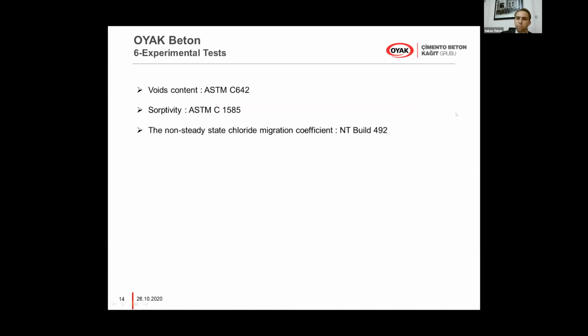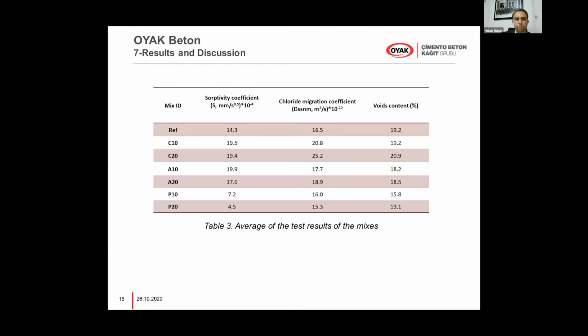And as I said, we have the previous 3 different test methods. One of them is void content in accordance with ASTM C642, the sorptivity test ASTM C1585, and chloride migration coefficients in accordance with NT Build 492, which we have already performed. Here you can see all the results. The reference mortar has a sorptivity result of 14.3, chloride migration coefficient of 16.5, and void content of 19.2.